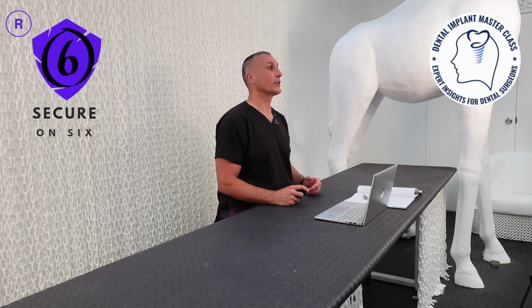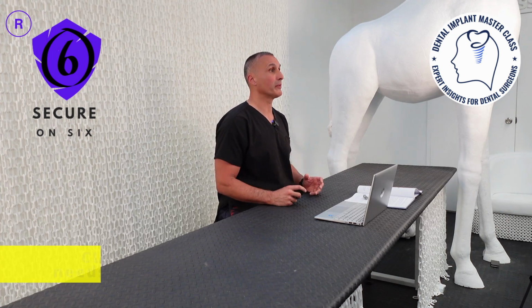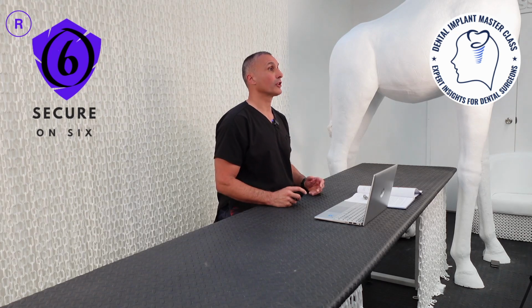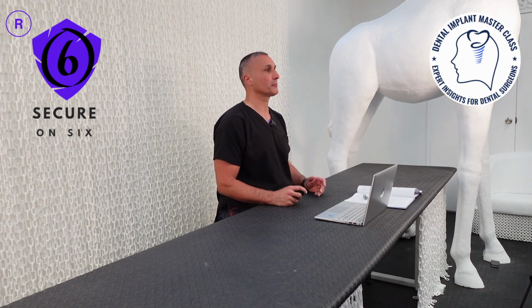Occlusal forces applied during chewing generate bending and twisting moments on the implant abutment connections, influencing screw performance. Therefore, bruxism and parafunction need to be carefully managed in patients with implants, because they have zero proprioception from the implants. And in fact, the data has revealed that patients with implants tend to have even higher occlusal forces than patients that are dentate. The direction and magnitude of occlusal forces and bending moments vary based on the patient's chewing patterns. Clinical practices such as repeated loosening and retightening of abutment screws can lead to smooth micro irregularities on the contact surfaces, reducing the friction coefficient and decreasing the preload over multiple cycles.